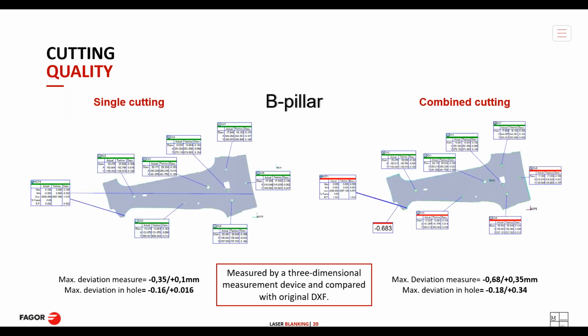Here we can see two examples of real blanks, and these blanks have been compared with a 3D pattern and measured by a three-dimensional machine. And as you can see in the left part, it would be a single cutting operation, and the deviations are between minus 0.35 and plus 0.1. And the deviations between holes, those holes used for some of them for guiding in following processes, are between 0.16 and 0.016.